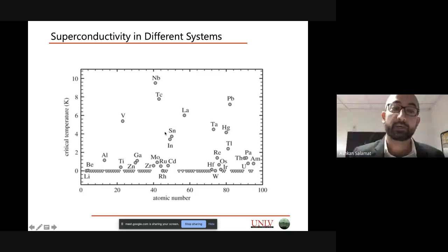But the elements themselves, although most, in essence, all of them should superconduct if they're metallic, they generally have very low superconducting temperatures. So below this temperature, below 9 Kelvin, is when niobium becomes a superconductor. That's minus 260 degrees. It's completely technologically useless.